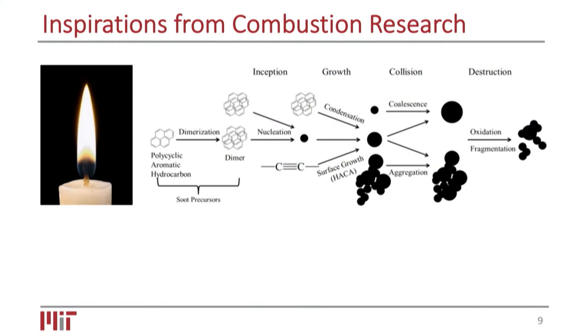But what the process is, this is actually taken from my PhD thesis, is that the precursors come into play as hydrocarbons, and when incomplete combustion happens, we get some gaseous species called PAH molecules. As they grow inside the flame without being fully oxidized, we actually form particles from this process. Whatever cannot be fully consumed in the flame will go out, so you would see the black smoke. Those are composed of this particulate matter.